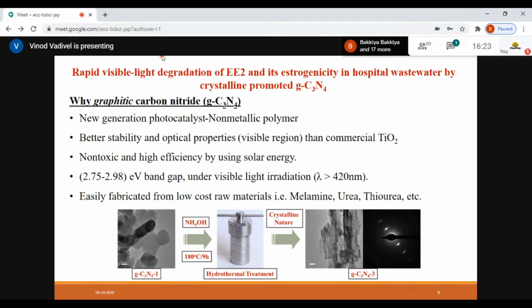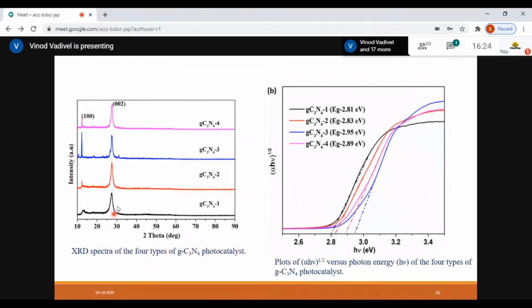So here, in this image, I'll summarize. GC3N4, which I say is the bulk material, is amorphous. You can see from the plot, it's an amorphous phase. And when you take this material into a hydrothermal treatment process using a precursor like ammonium hydroxide, you enhance the crystallinity of these materials, and you find these materials becoming more surface modified, crystalline, and assisting the enhancement of EE2 degradation. We proved this by PXRD spectra.